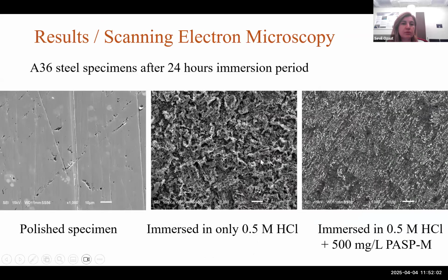And these are the results for the surface morphology. We have three different cases. The first one is the polished specimen. We have some scratches on the surface, but they come from the polishing process. The second one is the steel specimen immersed in only 0.5 molar hydrochloric acid, so there are a lot of corrosion products on the surface. And the third one is again hydrochloric acid, but this time with some inhibitors added to the solution.